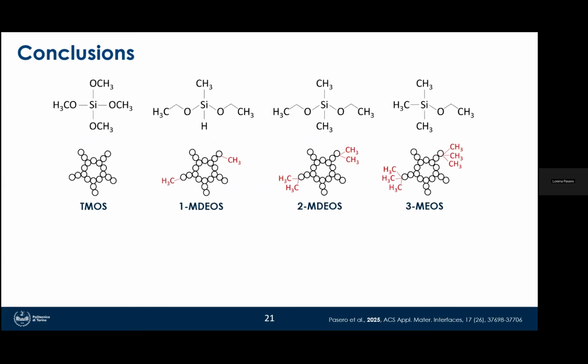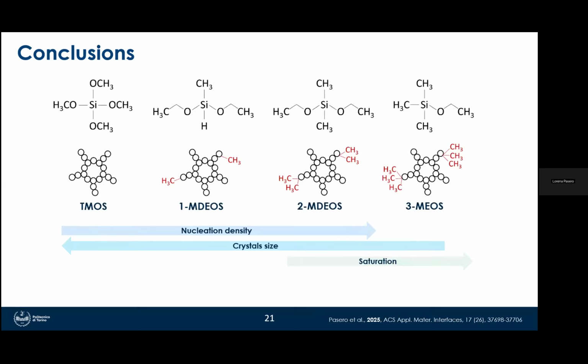So to conclude, we tried to modify the silica gels to control the nucleation and to overcome the inhibition effect of silica on protein nucleation. And so we could increase the nucleation density by increasing the number of methyl groups in the gels. This led to a lower crystal size, which could also be tuned through the gel modification, but a saturation effect was observed when too many methyl groups were introduced in the gel.